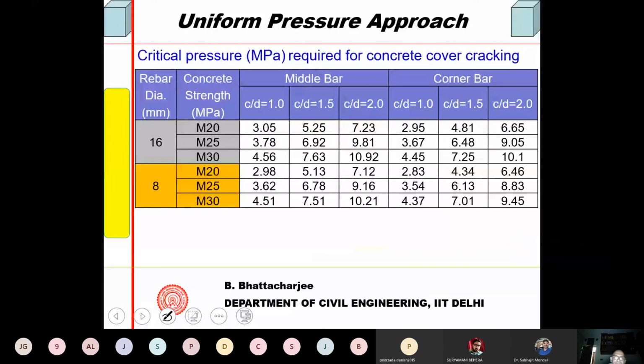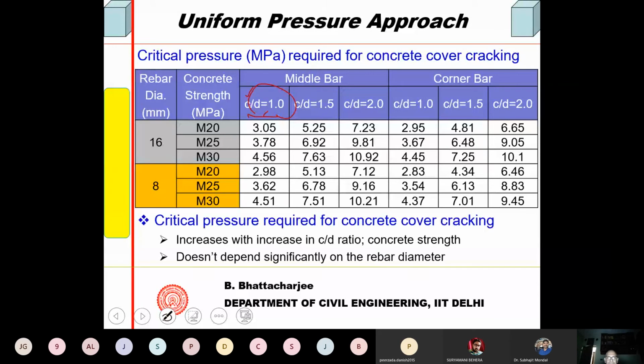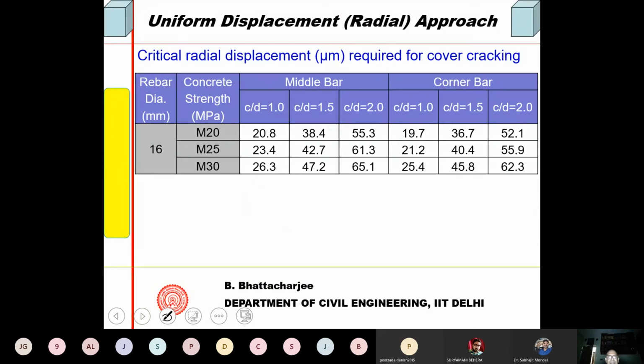Concrete cover cracking time. So for various rebar diameter, concrete strength, middle bar, center corner bar, individual bar, we try to look into. For different C by D ratio, C is the cover to diameter ratio, and critical pressure required for concrete cover cracking we could obtain. Concrete cover cracking increases with C by D ratio, etc. Modeling is possible, but validating is important. Critical radial displacement for bar also one could obtain.